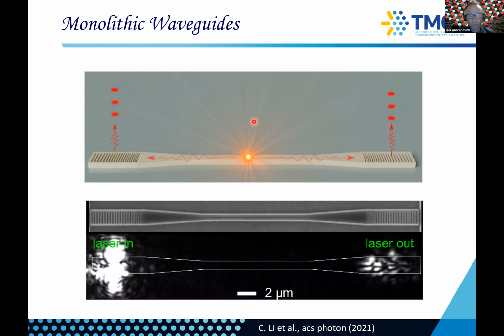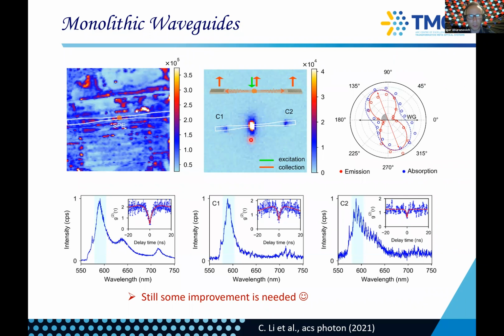Okay, so how do we then kind of try to interface the whole thing? So we need some sort of waveguides. So we also made monolithic waveguides. So this is just a hBN monolithic waveguide. And so that's how they look. So we can make an emitter in the middle, and we can collect the light directly from that emitter. We can excite on one side and collect from one end, and we can excite and collect from the other end. So these are basically the middle, and this is C1, which is here. And this is the other end, C2.